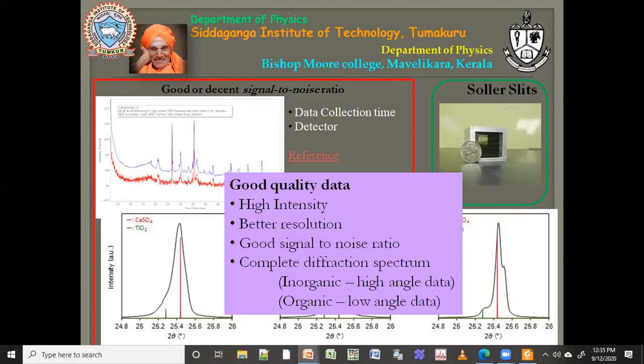If you take data at 800, it may not have formed and is not a pure phase. In that case you can just do a very quick 10 minute scan with all big slits, all big Soller slits. That is fine. But once you are sure it is a pure phase, you can ask your operators to scan for a longer time with better optics.